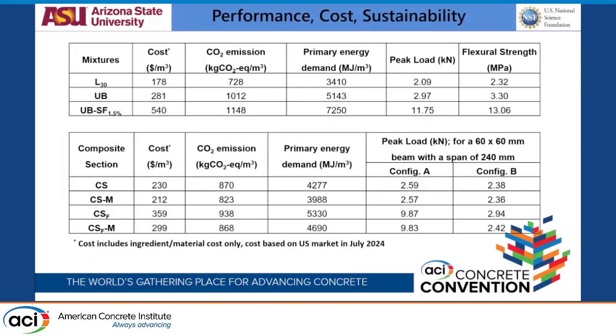Based on this, we did the carbon dioxide and cost estimation for these mixes. The top table is the homogeneous beam versus the bottom, which is the composite beam. Here the AM modified means, I showed you results for three layers, which is basically half of the beam. The modified AM represents 2/3 of the beam being replaced. Why don't we replace more of the UHPC mix with the L30? Because towards the compression side, we don't need that much strength, right? So these are comparative values for half of the section and 2/3 of the section being replaced.